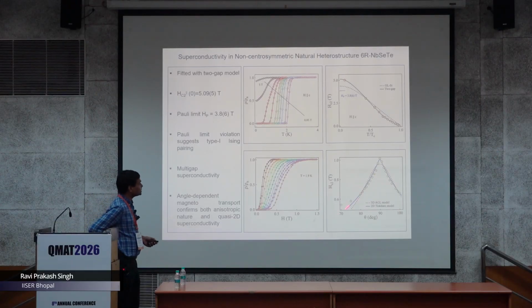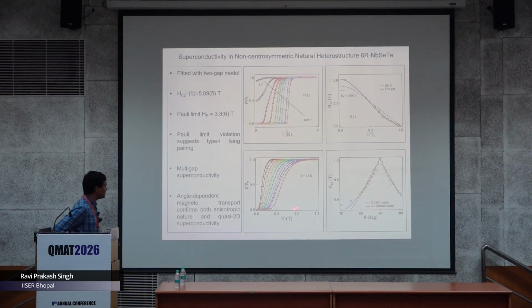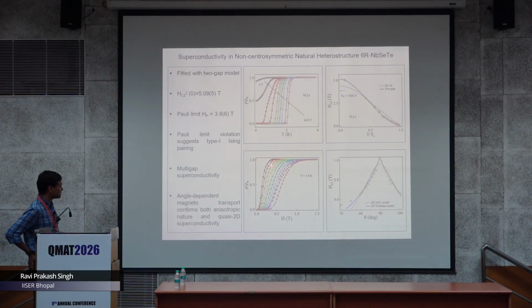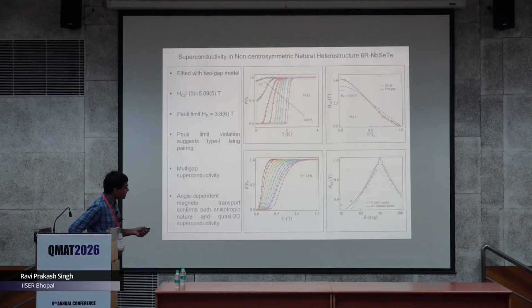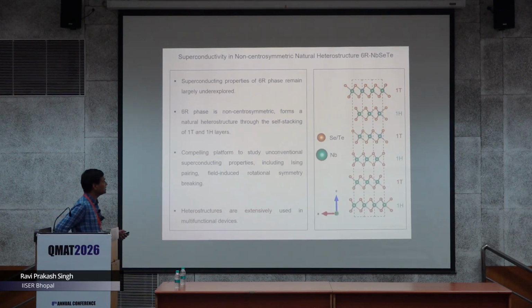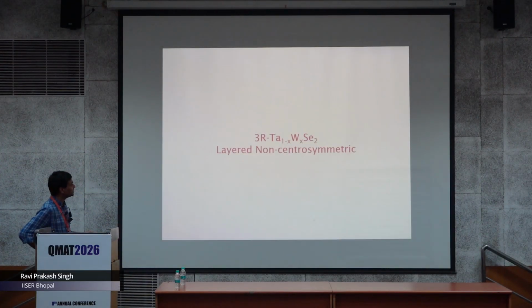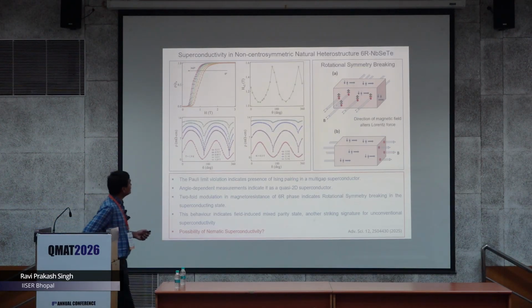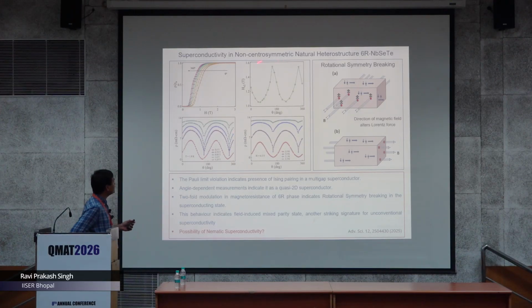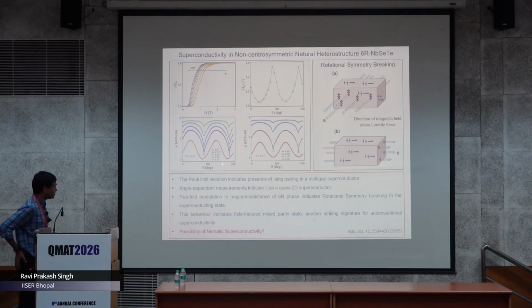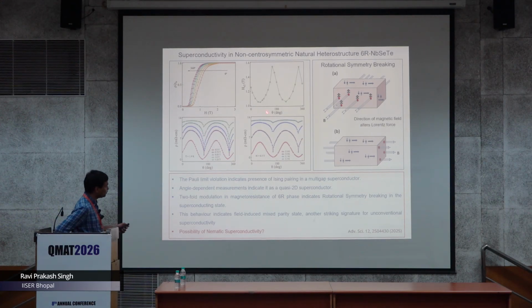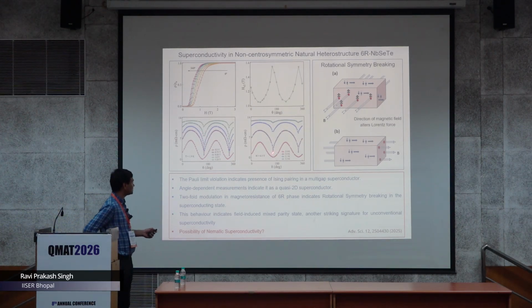And it is also showing the 2D angle dependence of the upper critical field, well fitted with these 2D models. So it looks like interlayer couplings are weak, and it is showing quasi-2D behavior. And surprisingly, when we did further angular dependence of the Hc2, we are getting a twofold rotation, like twofold variation of these